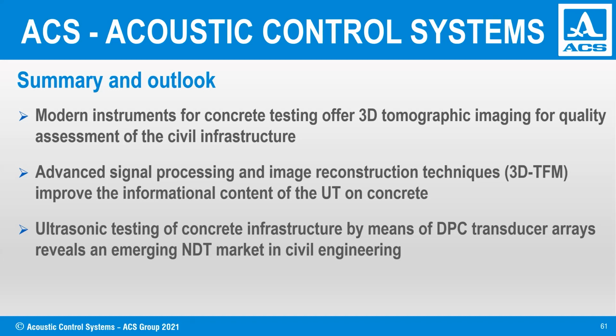It is nearly the same with metal testing. For metal testing, like weld inspection, we first calibrate the instrument on reference blocks. The problem is metal is a rather homogeneous material, not strongly dependent on the material properties. Of course, there are ferritic steels and austenitic steels, but for the most common ferritic steels, you can even use the same calibration block to calibrate any instrument for any use. Unfortunately, with concrete, it is not the same.